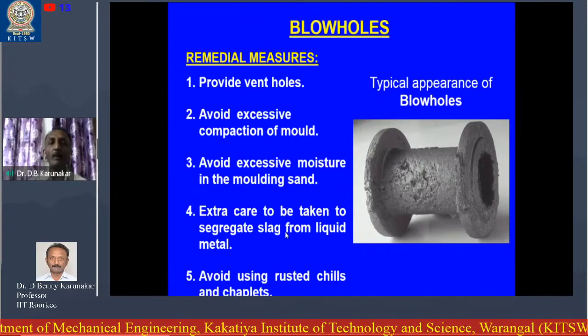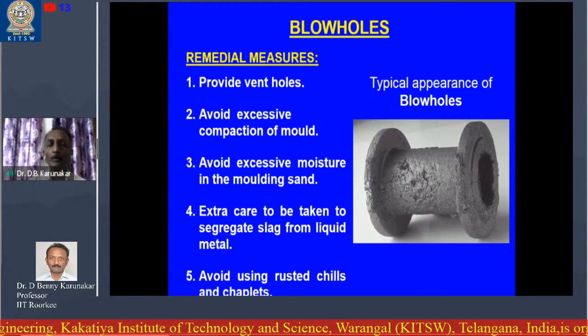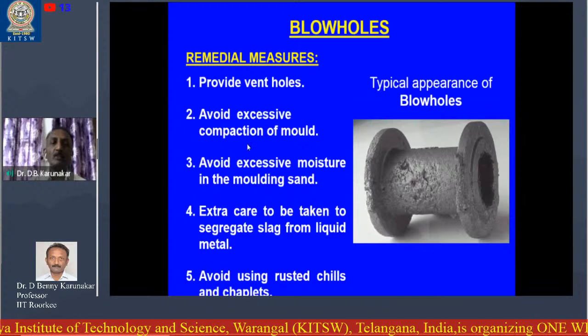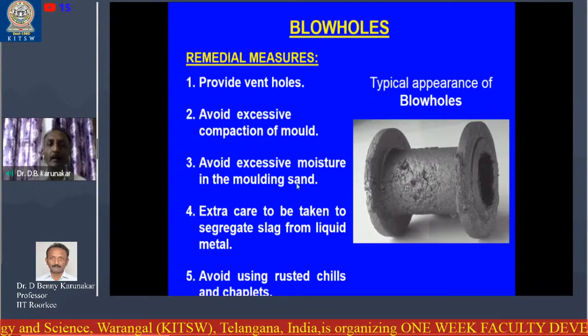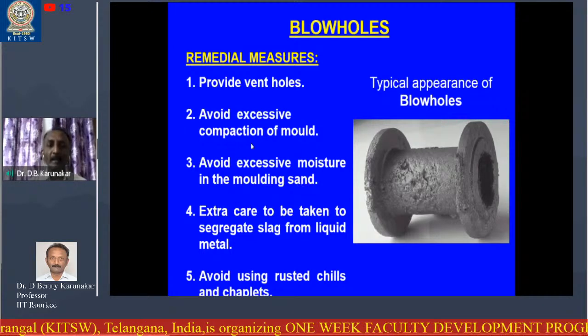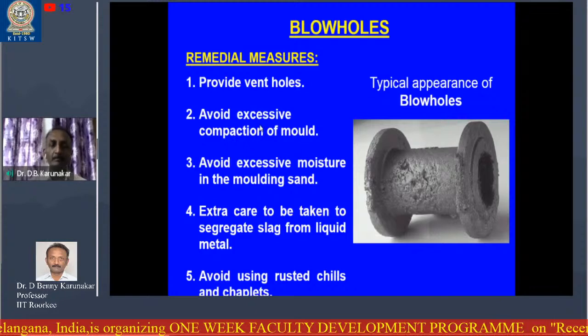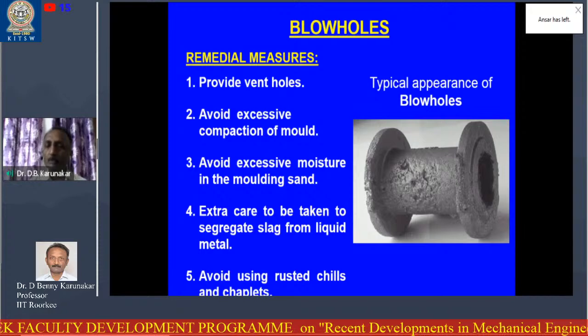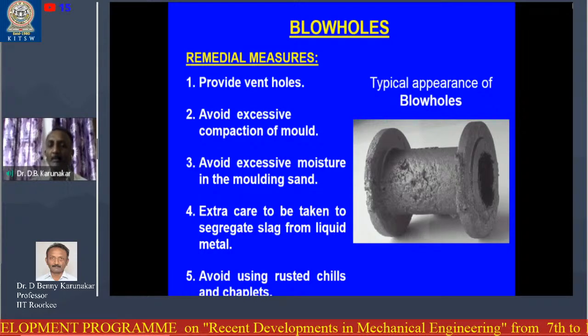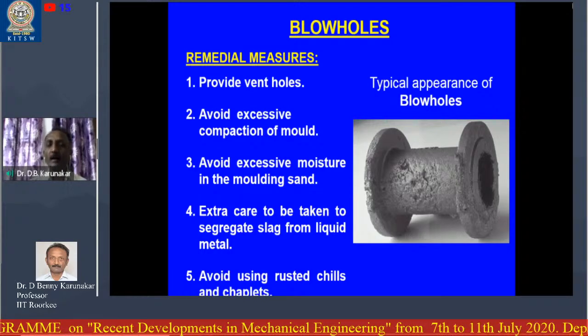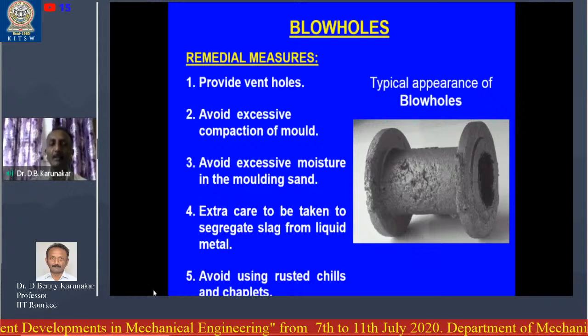Now, what are the remedial measures? Provide vent holes. Excessive moisture should be avoided, and excessive compaction should be avoided. Once you compact too much, the mold becomes too hard, permeability comes down, and the moisture and gases cannot escape.